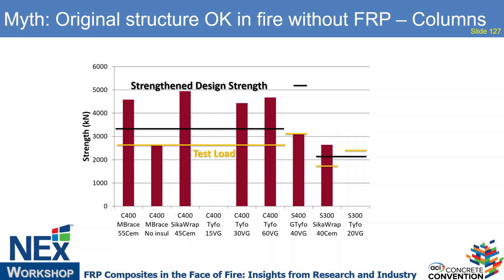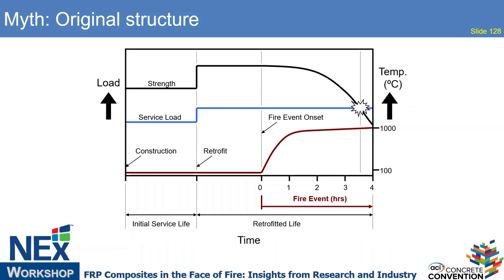I think we got about 3 hours of fire endurance, but still quite a bit less than the insulated columns that lasted 4 to 5 hours, and we had to increase the load. So you can see it failed at a lower load. But, you know, it might be fine for a 2-hour fire rating or something like that. Just worry about flame spread and things like that. And once again, Dr. Kruder had similar things showing about what happens.